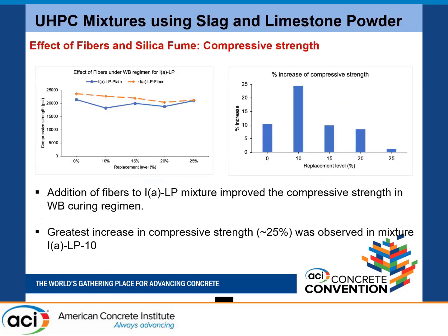And then there are some effects of steel fibers and silica fume here, with various replacement levels of limestone powder. Obviously, if you look at the graph on the left side, the fiber reinforced UHPC orange bar is producing greater compressive strengths when compared to plain.